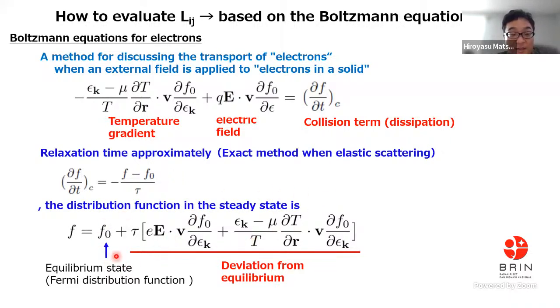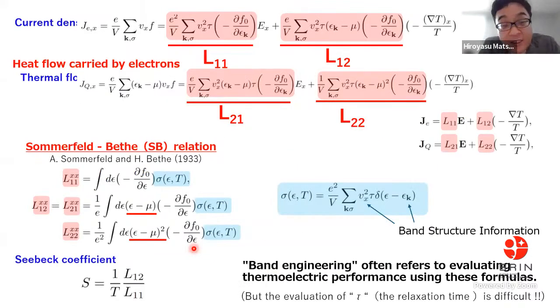In this equation, f is the distribution function in the steady state, and f0 is the distribution function of the equilibrium state, which corresponds to the Fermi distribution function in the electron case. And we have additional terms coming from the temperature gradient and the electric field. Using this equation, we can derive the electrical current and thermal current like this, and by comparing, we can get L11, L12, L21, and L22. Using this, we can summarize the equations.